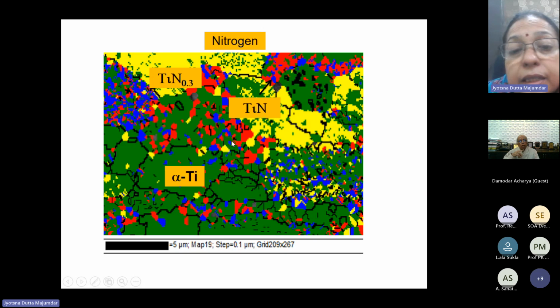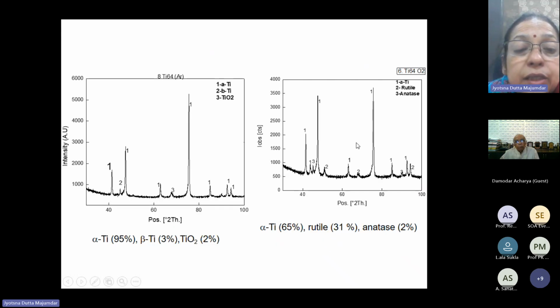So these are again EBSD. We try to just map the phase, but this is a relative measurement technique. We try to see actually, but it was confirmed by EDS analysis rather, to know whether these are actually these phases.